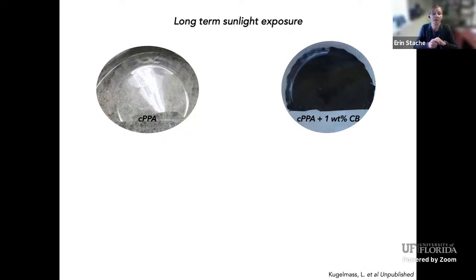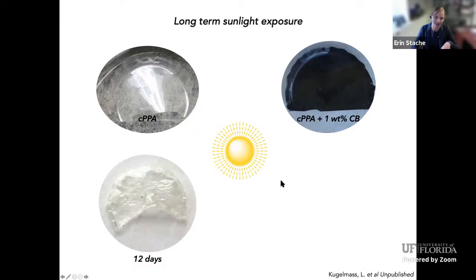And so we took a film of cyclic poly(phthalaldehyde) without any carbon black, and then a film that has 1 weight % carbon black in it, and just set them on the windowsill for an extended period of time. We get very good sunlight in the afternoons on that windowsill. It gets very, very hot actually. And after 12 days, you can see that the polymer is starting to degrade if it doesn't have any carbon black in it. It's starting to yellow, wrinkle up, and shrink.